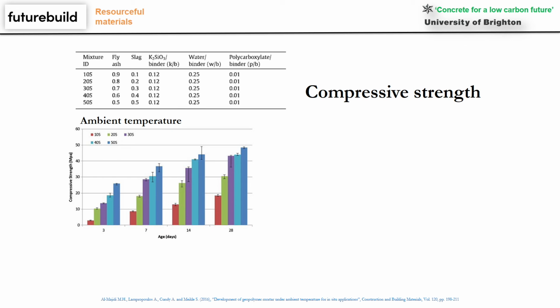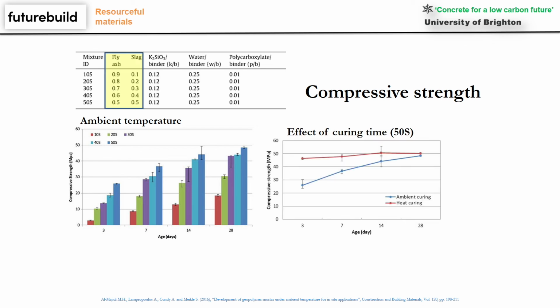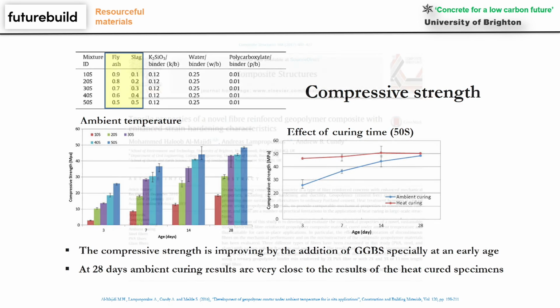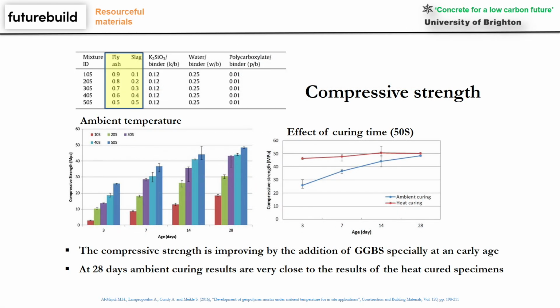So actually, we had different percentages of fly ash to slag ratio, and we checked how this affects the strength, but also we checked how this affects the workability. So the workability is a quite crucial point when you work with these materials. So practically, the more you increase the GGBS, the less the workability, but the higher the strength. So we ended up with our mix composition, which is good for in situ applications, but also has good workability.